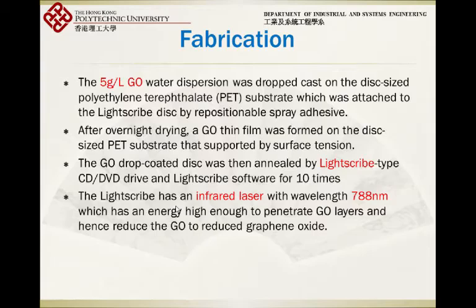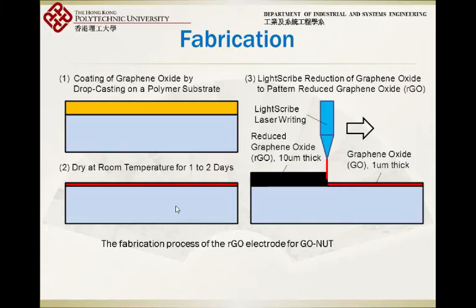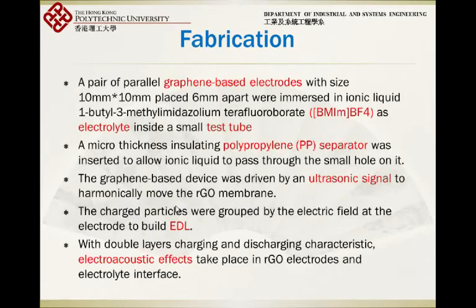So this is the type of drive you need, and it uses infrared lasers at 788 nanometers. And this is the process. You just first drop cast the solution of graphene oxide, and then you wait for it to dry, and then you can start to do the laser writing using the LightScribe DVD. So this is the process, very simple.